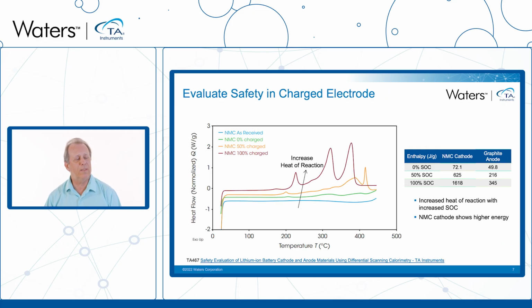And then in this particular slide here, we show that we can actually study how these exothermic transitions are affected depending upon the state of charge in the material. So from this graph here, you can see that we, first of all, have an overlay of several different states. First of all, we have the NMC as received. So this is just as it comes in, hasn't even been put into a battery yet. And then we have the NMC left in a 0% charge state. So again, the battery has been through several cycles and then brought to a 0% charge state, disassembled, and the material put into the high pressure capsule as stated before. And then we have 50% and 100%. The 100% data is the data that you saw on the previous slide.